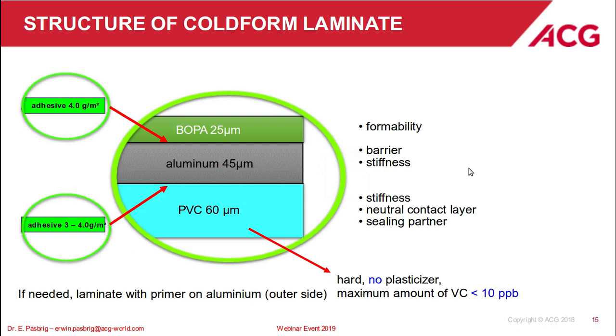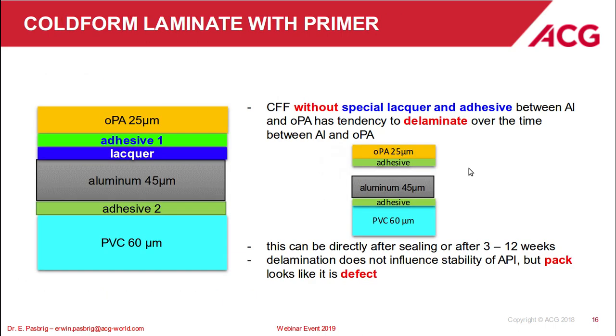The PVC we are using is hard PVC and does not contain any plasticizer. The maximum amount of vinyl chloride is less than 10 parts per billion, as the FDA requirements are. As you know, for thermoformed materials, it's less than 1 part per million. The reason for the reduced amount for cold form laminate is that if you close the blister, with aluminium on both sides, what is inside stays inside, and the vinyl chloride can migrate into the packed product, and vinyl chloride is harmful for the human body. We can produce both kinds of structures, with and without primer on the aluminium on the outer side.